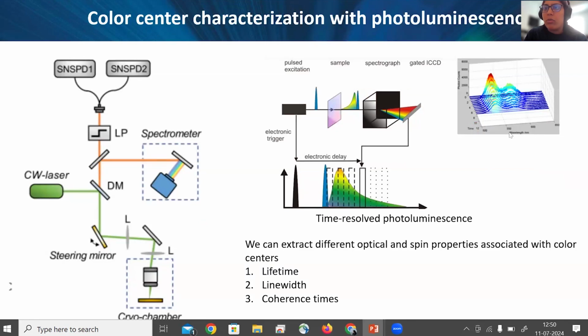And then when it comes to how we characterize them, it's basically using photoluminescence. You essentially excite your defects or color centers, and then sense the signal coming out of your sample. Depending on what color centers you form, if you use the spectrometer, you will see the signal as a function of wavelength. And with some modification in your setup, you can have time resolution as well. So you can not only take a single static spectrum, but also know the lifetimes, how the emission is changing as a function of time, and also other properties like the spin coherence times, that you can do with photoluminescence.